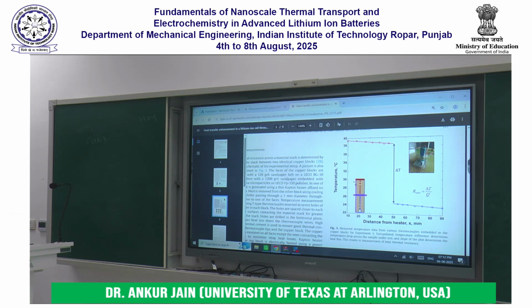Then there will be the thermal resistance which we are calculating. Yes, it must have affected it in some way, but we made the argument that since the thermal conductivity of the electrolyte is so low, it probably does not offer a good heat transfer path for heat to pass through. Looking back at it, this was certainly a weakness of this paper in that we could not quite measure the thermal properties in the presence of the electrolyte.